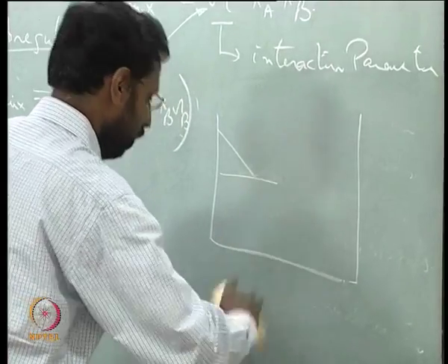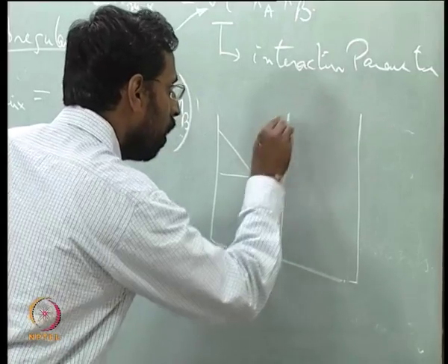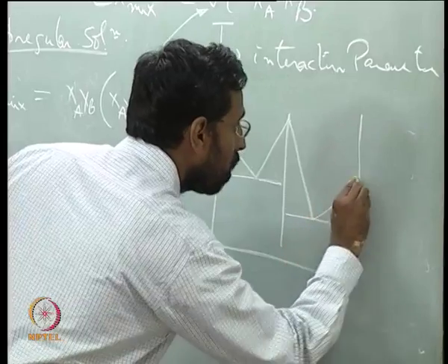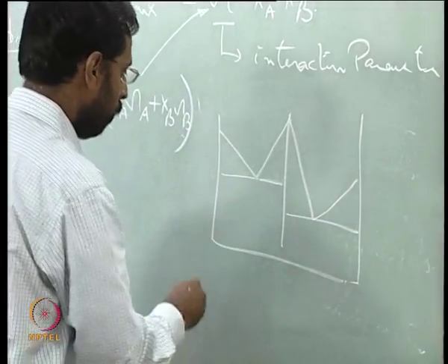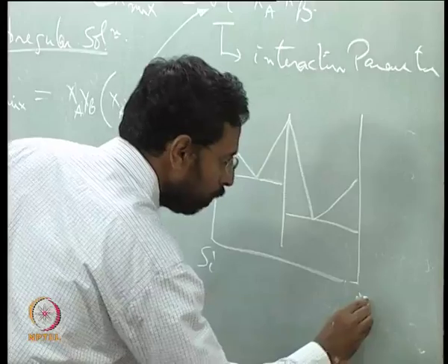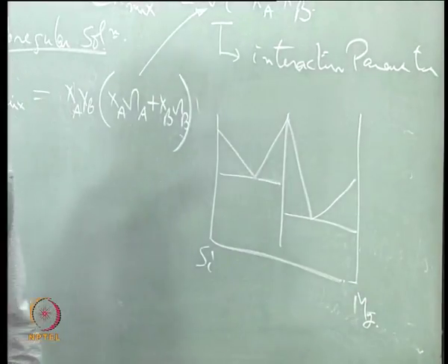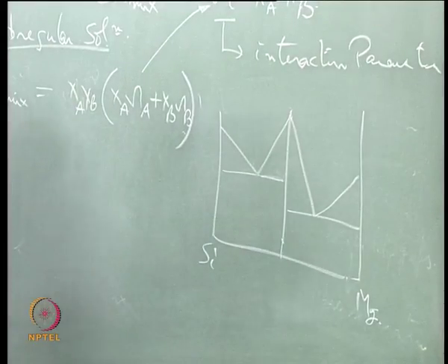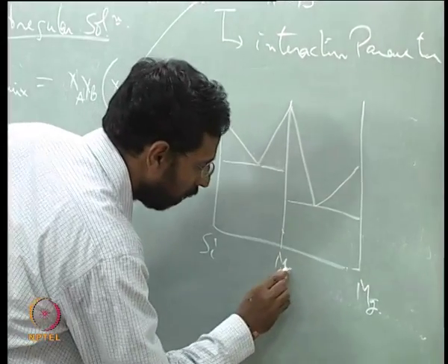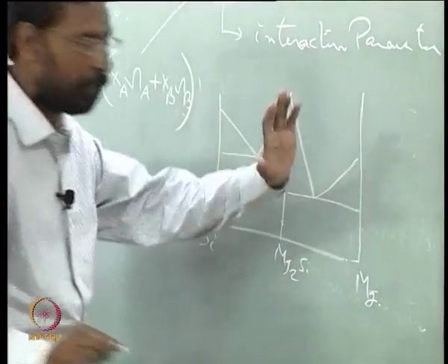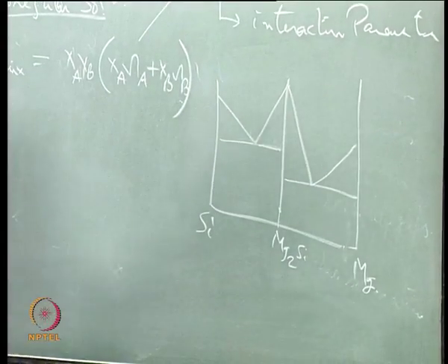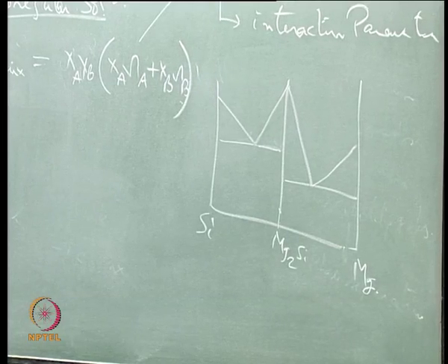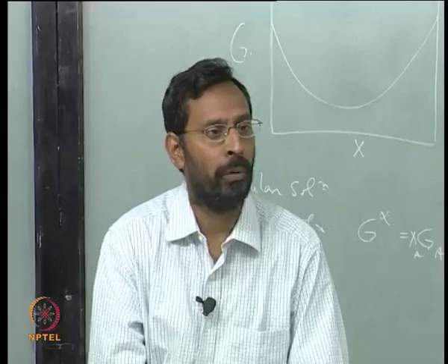No. Okay. If you have not seen it, I will not bother about the actual temperatures much, but give you a schematic. Obviously this should be the silicon side, this should be the magnesium side, and do not bother about this at the center of the phase diagram, but this is actually Mg2Si. So that means this is on the magnesium side. So you see a phase diagram like this, it has two eutectics and one compound.